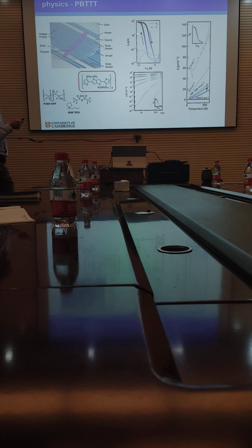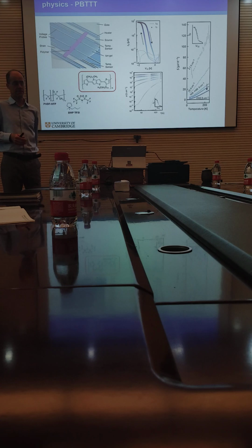This is dialing in this high conductivity state, and then you can measure the conductivity as a function of temperature. It's pretty metallic, so pretty temperature independent. Then at this condition here, if you set this gate voltage, you see a more insulating characteristic where the conductivity drops strongly when you reduce the temperature. Here is the corresponding Seebeck coefficient. It's p-type, so it's hole transport. As you increase the gate voltage and move towards the highest conductivity state, the Seebeck coefficient drops and reaches values around 15 to 20 microvolt per Kelvin at the highest conductivity and has this characteristic linear temperature dependence. So that's all what you would expect.